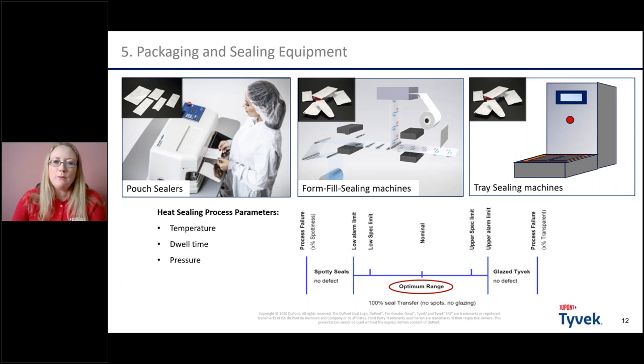Which are, for example, with two cavities, and you put here the empty tray, you put the device into the cavity, and then you put the lid on or lids on, and then you close like a drawer, and then it's sealed. So all those have in common the process parameters for the heat sealing. So it's temperature, dwell time, and pressure usually.